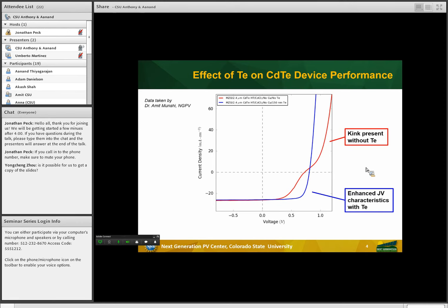Adding a tellurium back contact to the device establishes JV characteristics that allow for efficient carrier collection and significantly improves the device performance. However, we're left with a question that is difficult to answer with experimentation alone. And that question is, what are the main mechanisms in tellurium that cause such a benefit to occur? That is why we are using DFT to investigate why tellurium is so beneficial to the CdTe device.